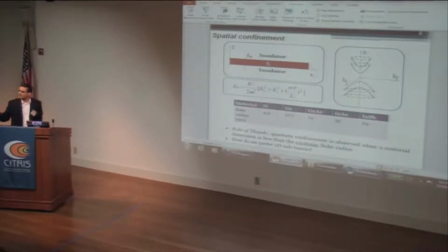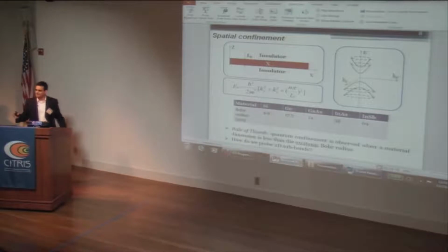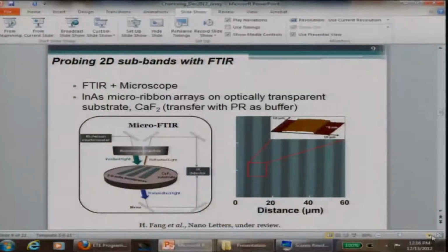confinement. Of course, you can get quantum confinement induced by the gate fields. For indium arsenide, on the other hand, the Bohr radius is 35 nanometer. So any film that you make below 35 nanometer is going to be quantum confined. And the thinner, of course, the more drastic the quantum confinement effect is going to be. So the question is, can we probe these subbands that are forming and look at the drastic effect of quantum confinement on the band structure, on the band gap of our, in this case, indium arsenide? And if so, how do we do it?